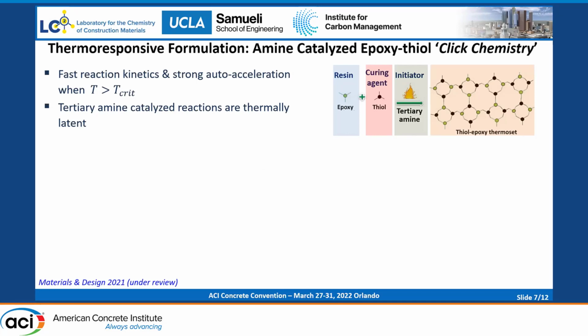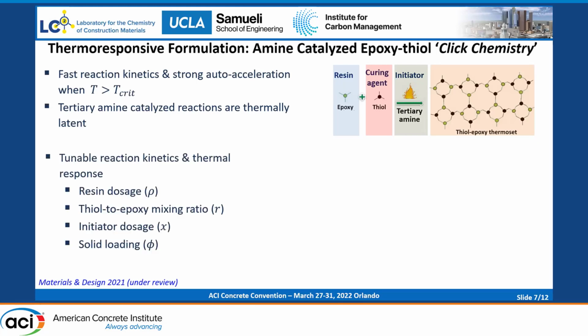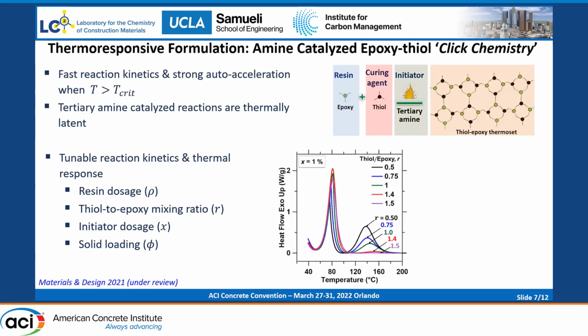And once the reaction is started, it is a highly auto-accelerated reaction once it is initiated. So the epoxy is the resin, the thiol is the cross-linking agent here, and tertiary amine is the initiator or the catalyst. So choosing this initiator is very critical because this is what decides the activation temperature and the reaction kinetics. The biggest advantage of this formulation is it gives us a lot of control over the thermal response and the mechanical strength of the printed or the cured composite. The controls are the resin dosage, thiol to epoxy mixing ratio, the initiator dosage, and the solid loading.